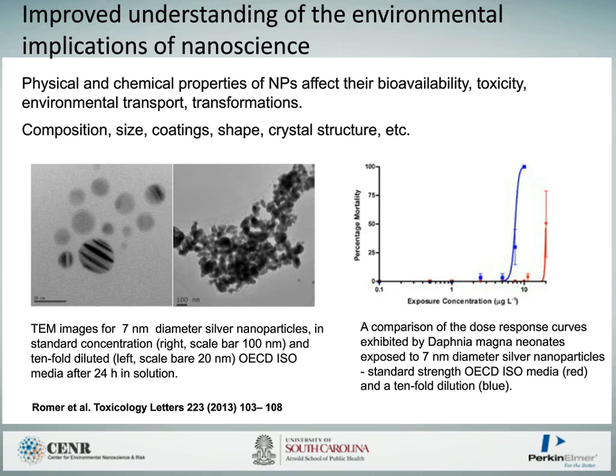So you get large aggregates of these originally small particles. On the left-hand side, we see a TEM image of the particles which are exposed to the same iso media but diluted by a factor of 10. So the salt concentration causes aggregation at high concentrations, but at low enough concentrations, these particles are slightly changed from the original, but they're still dispersed. And so you get different types of the original nanoparticle that the organisms see.